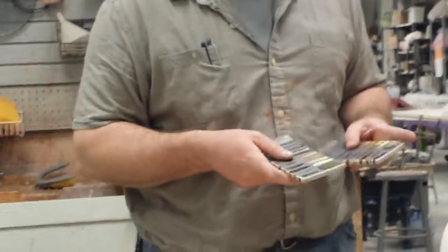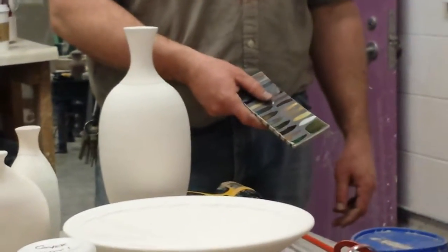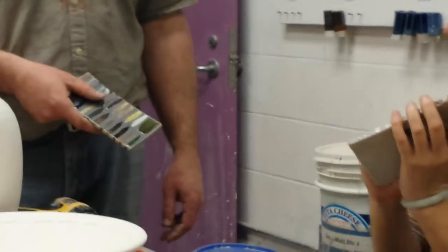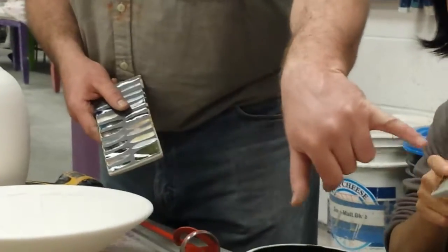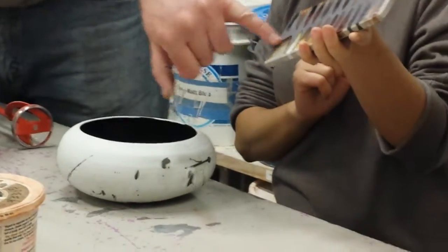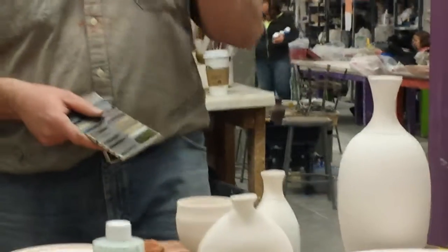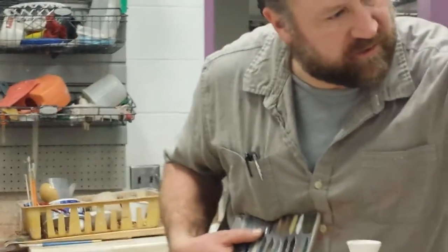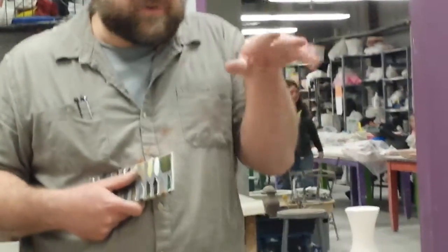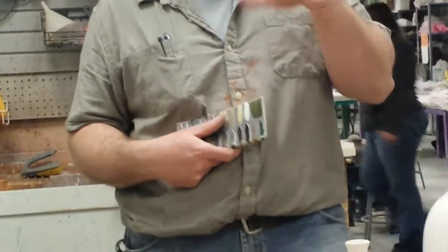With the iron slip and the white on this one — does this defect always happen? No, not always. Up in here where you see the dark, that's probably where the slip or the glaze was a bit thinner, so you've got more of the iron coming through. And where it looks more like clear glaze, the slip was maybe a little thinner or the glaze was a little thicker — could be a combination of those two things happening. Maybe a little bit thicker on the slip and a little bit thinner on the glaze.